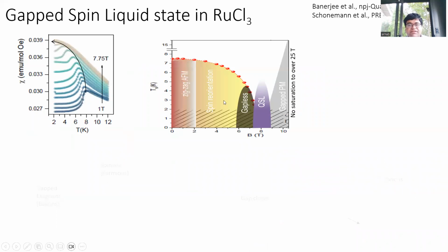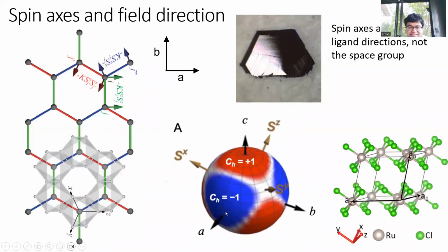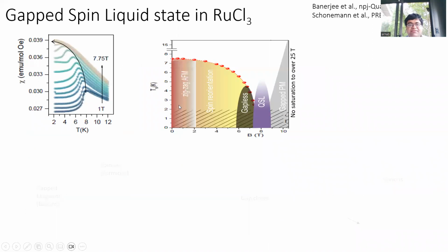So our next result: we were trying to apply the field along this H parallel to A, so the field along this axis, cutting across these bonds. That's the direction in which we apply the field. And what we figured out is that it is indeed possible to get rid of the long-range ordering. And here's the phase diagram that we got.